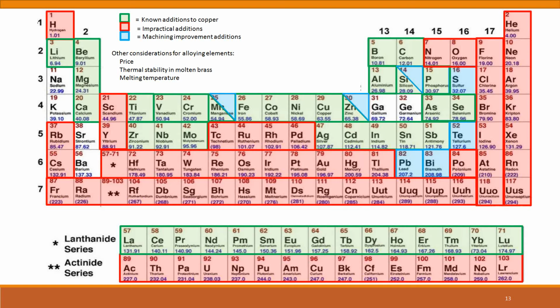What that leaves you with are the elements that are in green, which are standard alloying elements to brasses. The elements that are in blue are the ones that are added for machinability, and the ones that are half green and half blue triangles are the ones that work together to make a more machinable material. A lot of the elements in there are there for corrosion resistance, for strength, for high temperature resistance. There are some really exotic ones like chrome and niobium that are made as tiny particles and added to copper to make heat shields for the linings of nozzles in rocket engines. There's just a lot of different things that are used for the best mix of elements to get you the properties that you need.